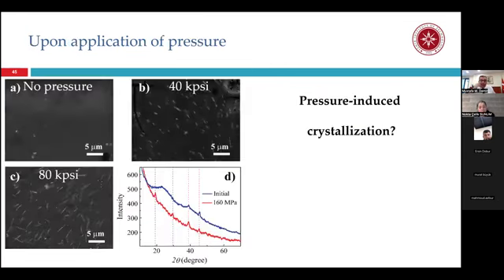Interestingly, when we apply mechanical pressure, we realize some crystalline domains form in the structure of the polymer. In the electron microscope image, you see some rice-like structures. They most probably are crystals induced by high pressure. We follow the crystal formation in the diffractogram: the blue one is the initial one. After application of mechanical force, you see a new set of reflections, which shows the formation of crystals.